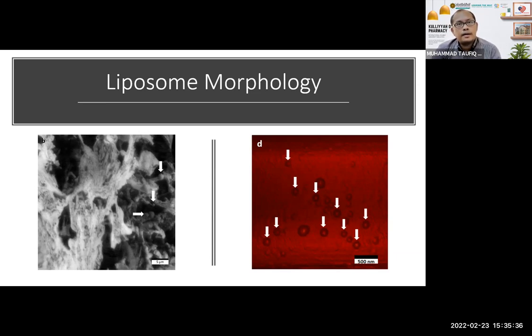Now, this was taken after I mixed the whole aqueous phase with more trehalose. Initially, the aqueous phase of the formulation also contained trehalose, but a smaller amount on the inside, meaning that during the fabrication I used a smaller amount of trehalose, and then after I purify it, I increase the amount of trehalose outside of the liposomes. There are some difficulties in this as well, because as you can imagine, the higher the amount of trehalose you put outside of the liposomes, the more likely that water will come out from the liposome because of osmosis.